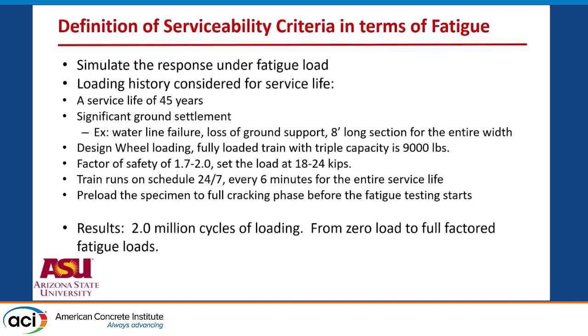So we went backwards. To simulate the response under fatigue load, we looked at the service life, 45 years. And then the question was, what is the damage criteria that we're going to look at? The hypothetical situation was, what if we have a water main failure underneath the track slab that washes away all of the ground support, something of the order of an 8-foot length. That's because in our lab we were very comfortable with testing that. And then the idea is that for 45 years, nobody notices that the water line broke, and there is no repair done, and you have to apply all of the load.